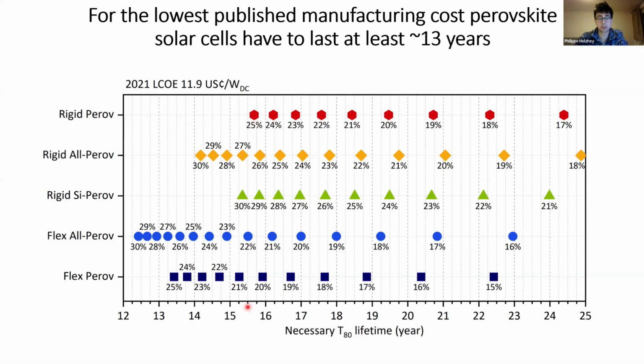So this is a parameter space which shows how different efficiencies and different architectures have to reach certain lifetimes. And it gives you a framework to know which lifetimes you have to get. And the change is considerable with different architectures because different architectures have different manufacturing costs and different efficiency limits. And the big thing in this work, which we published, was that with flexible solar cells, you can save in the balance of system costs. And that's why flexible solar cells, while at the same efficiency, need to reach lower lifetimes, because you can save on those balance of system costs. So the installation becomes easier. You don't need the racking, and you can easily store it. So it's quite nice about flexible cells.